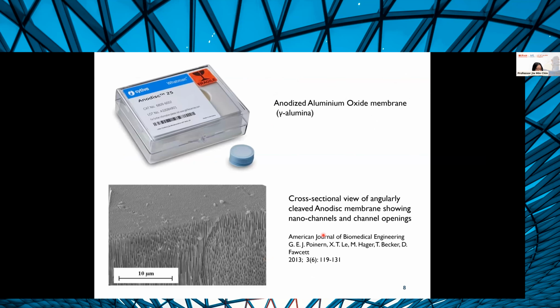So we thought, okay, let's try using a different precursor instead of aluminum nitrate. Let's look at gamma alumina as a precursor instead, because gamma alumina is quite reactive, and maybe it could serve as a substrate for MOF growth. So we took AAO membranes as our gamma alumina source, and the AAO typically looks like this. If you look at the SEM image, you've got a slightly rough surface, and if you cleave it, you've got these nano channels that run through the membrane.